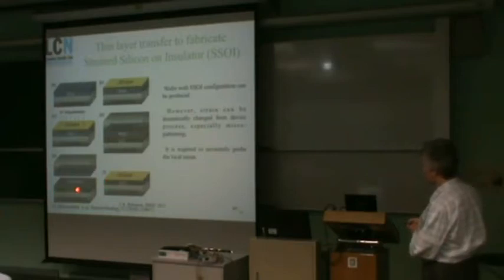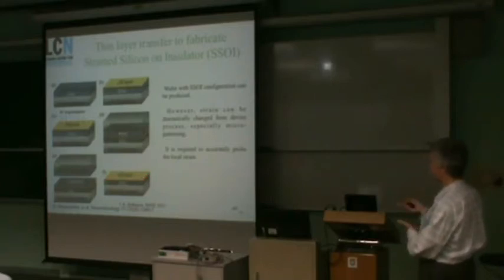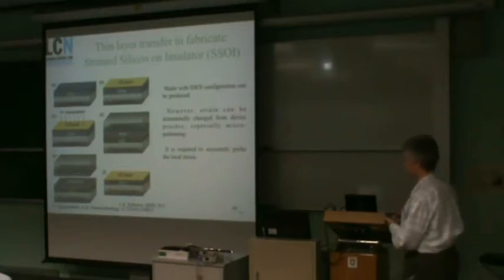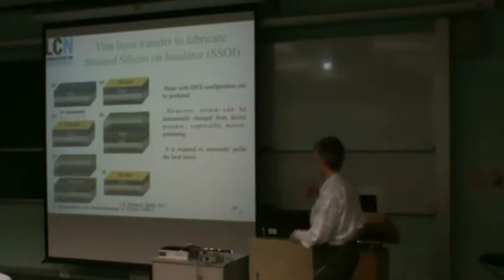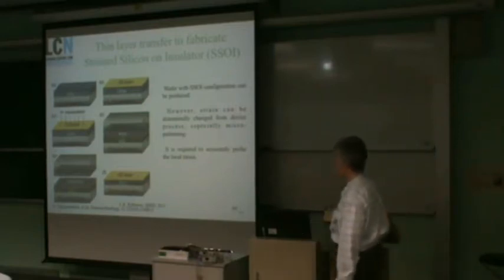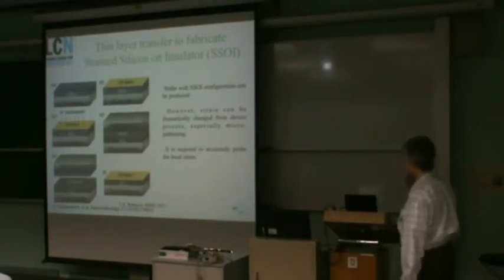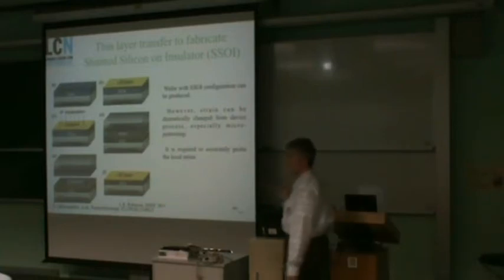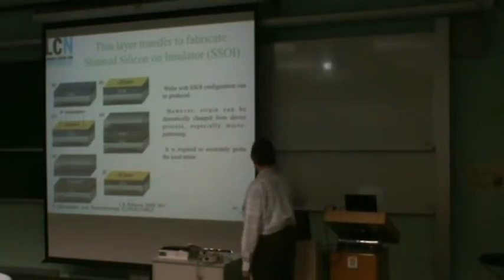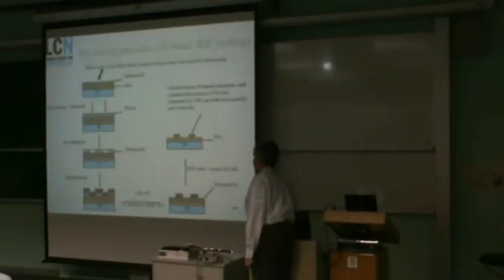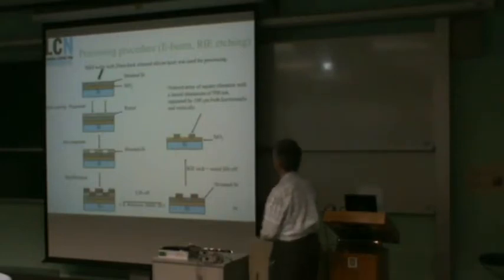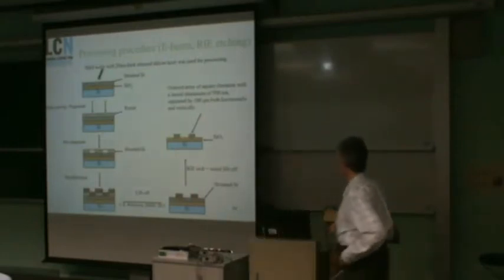Okay, so you then polish off the remaining silicon germanium, and you're left with a nice thin layer of strained silicon on top of an oxide layer on top of the substrate, and that's your wafer for subsequent processing with the strained silicon layer inside it. So we ask the question: if we take this material and start patterning it, are we going to see relaxation of the pattern of strain that's put inside it?